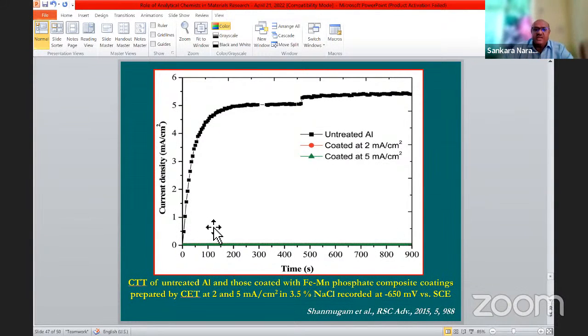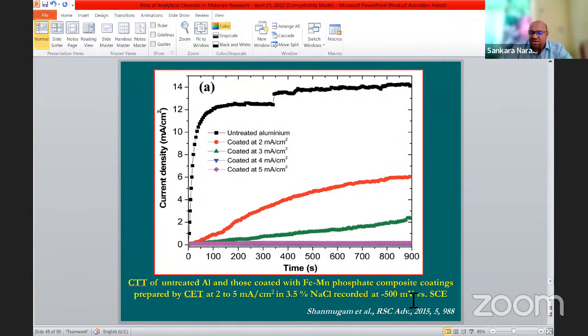For untreated aluminium, you can see there is a continuous increase in current. If we use the same experiment for the sample coated at 2 milliampere and the sample coated at 5 milliampere, the current is very, very less. So we can appreciate that there is a considerable change in the current density. This material is undergoing corrosion at a faster rate, and these two materials are not corroding much. If you want to distinguish between these two, what will happen? You make it slightly anodic, so you apply the potential of minus 500 millivolts.